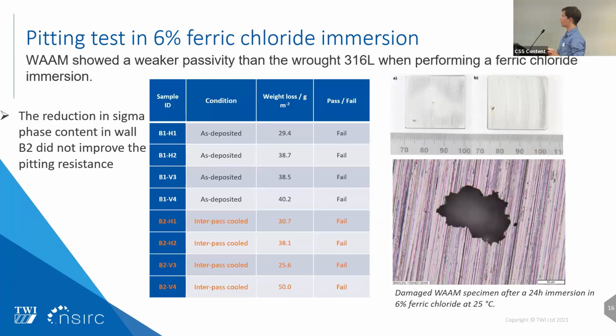The weight loss is calculated before and after the test, and you can see depending on the weight loss if you have passed the test or not. Here you can see we have high weight loss for all the materials, which sustain substantial damage, way more than what would be expected for a traditional 316L, a wrought 316L, which is supposed to pass that test with minimum damage.